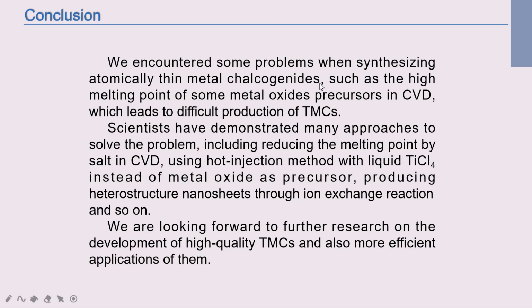So, in conclusion, although we encountered some problems, scientists have demonstrated many approaches to solve the problem, including reducing the melting point by salt in CVD, using hot injection method with liquid titanium tetrachloride instead of metal oxide as precursor, producing heterostructure nanosheets through ion exchange reaction, and so on. And we are looking forward to further research on the development of high-quality TMCs and also more efficient applications of them.